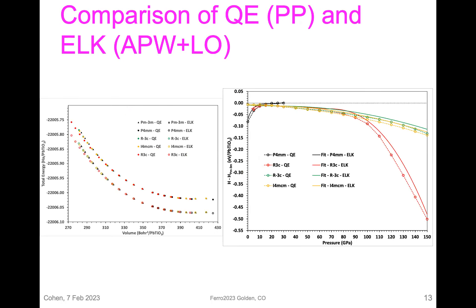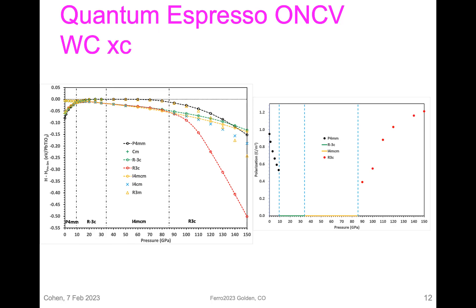I think that since it's a first-order phase transition going from the tetragonal to the rhombohedral phase, the tetragonal phase is just remaining metastably in the experiment. It's at the very top end of the measurements, and most of the measurements were done at lower pressures. So I'm trying to get my experimental colleagues to look again at higher pressures.